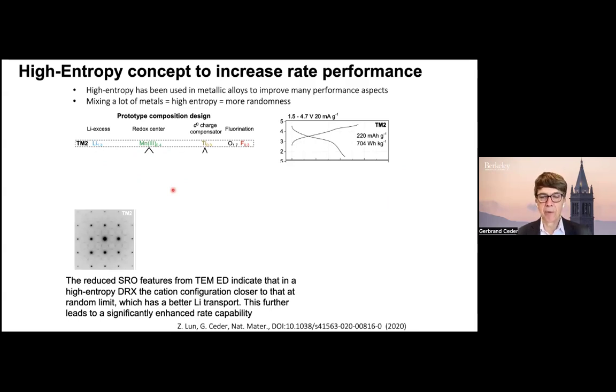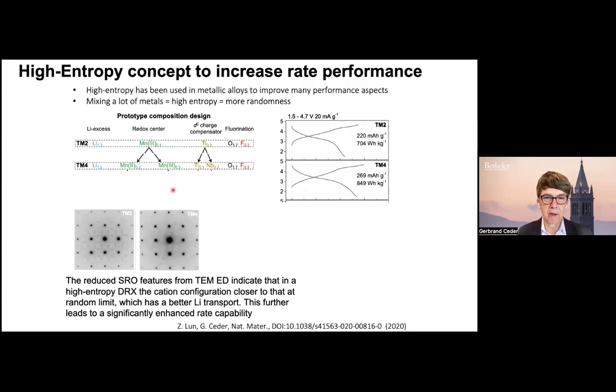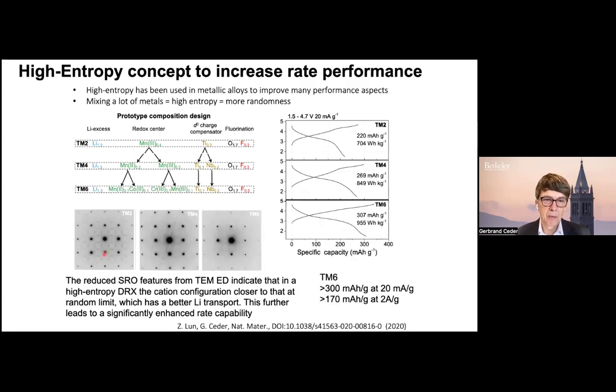So if you work with 2 transition metals or 4 transition metals or 6, what you see is this is 2, you get significant short-range order. This is 4, and this is 6. By the time you have mixed 6 transition metals, your short-range order is almost completely gone. And what you see is if you look at the performance, the more transition metals you have, even though we have the same redox capacity, we get higher specific energy. And this is same particle size, same electrode formulation, discharge at the same rate.